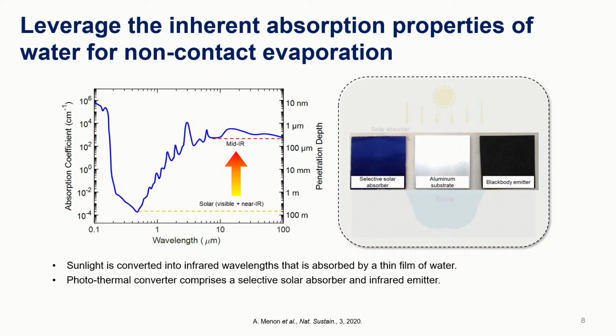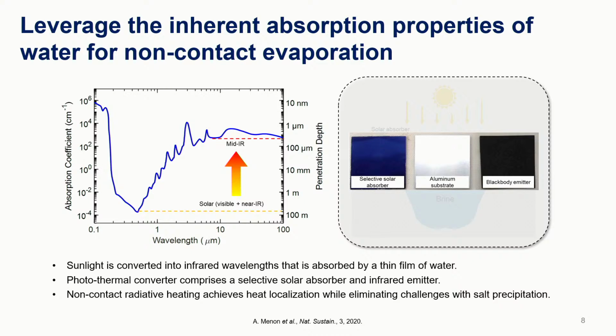So the material we need to use for that is a selective solar absorber. This is a multi-layered material, which again has an alpha or solar absorptivity of about 0.95, and it has a very low thermal emissivity. And so all the sunlight that's coming in is converted into heat by this material. And it is deposited on an aluminum substrate, and we're using a metal so that it can rapidly transfer the heat, so high thermal conductivity. And on the back side, we can use this black body emitter, or you could even design selective emitters to emit exactly at the wavelengths where water shows a strong absorption. And so this allows you, again, to do surface heating, and you do not have to worry about any salts precipitating because the entire process is just non-contact. So we're just using thermal radiation to transfer the energy.